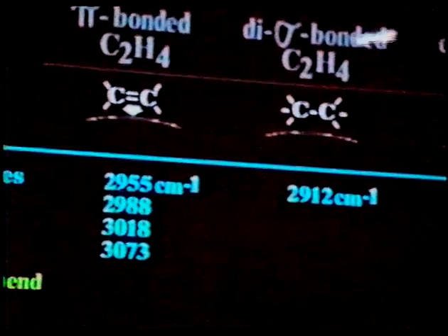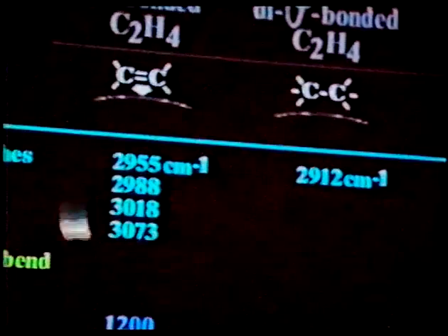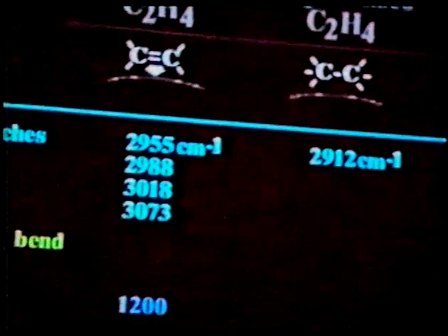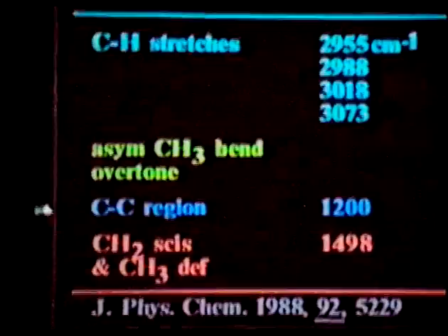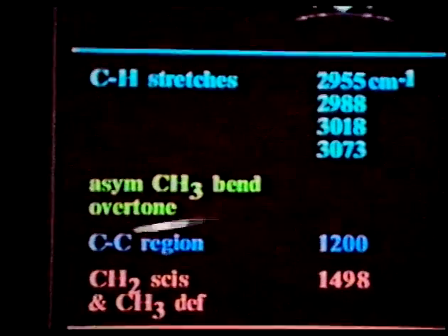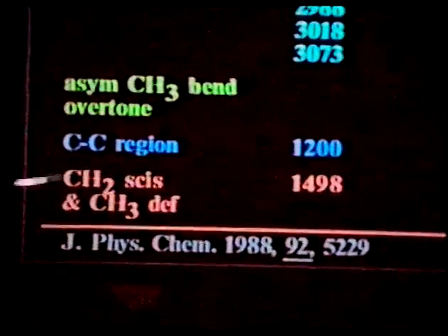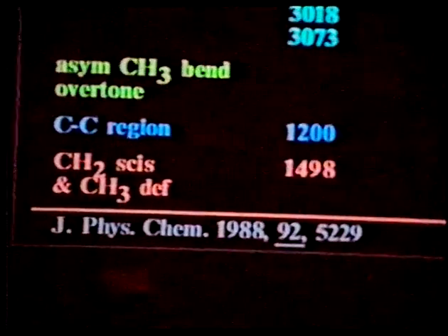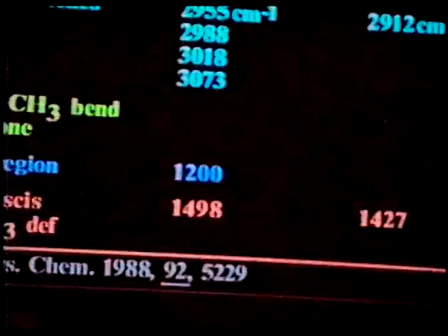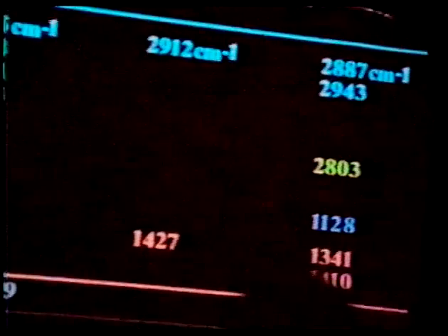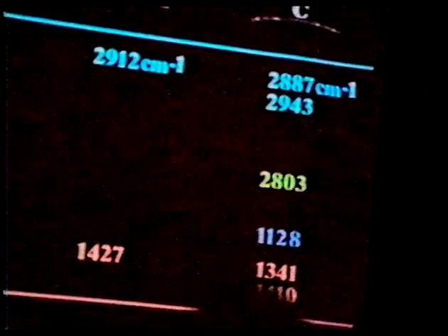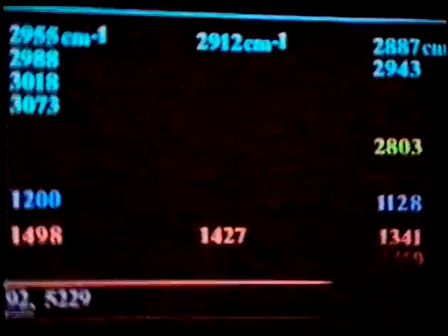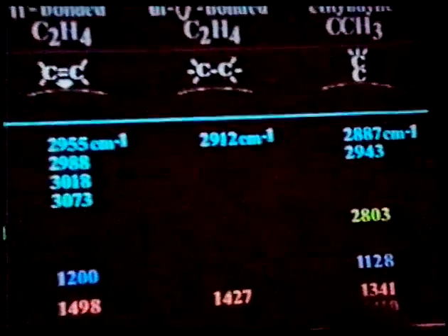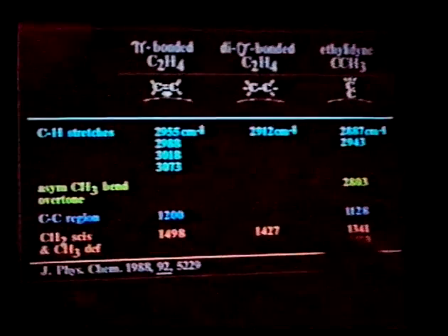The way in which we identify these species is shown by the variety of stretches that one can observe. For the pi-bonded species, there is a large number of symmetric and asymmetric CH stretching modes. There is a very strong 1200 wave number band in the carbon-carbon stretching region, and in CH scissoring type of motion, where you have in the pi bond the hydrogens swinging toward one another, you have also a relatively strong band. The problem one has to observe at times is the disigma-bonded species, because there are really only two bands that one can characteristically observe.